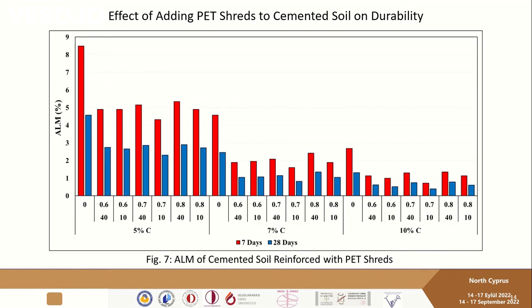Also, if we consider the effect of adding PET shreds to cemented soil on durability, we can see that by adding PET shreds, the durability of the cemented soil was being improved as the loss of mass was being reduced. But size number 10 was better in improving the durability of the cemented soil, and also by adding a higher cement content, the durability was getting improved more and more.